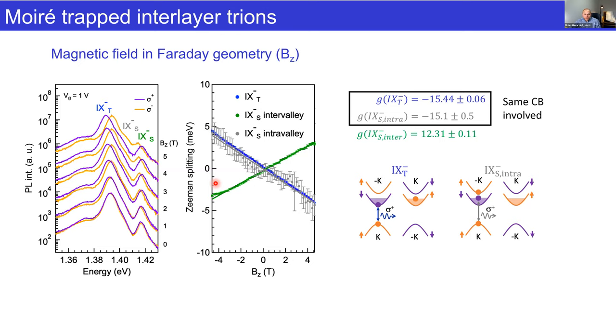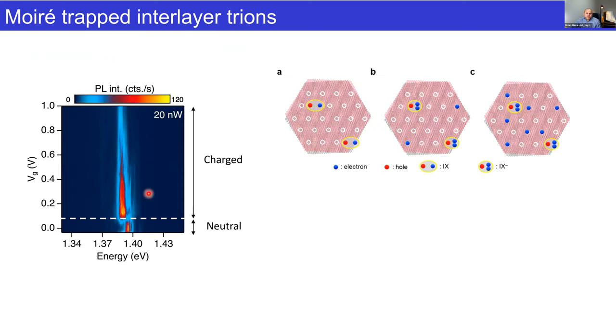So now this is the high excitation regime. If we go to the low excitation regime, this picture here, we can think about a Gedanken experiment, what would happen. We start in the neutral regime, where the white circles are the atomic registries of the moiré lattice, and we can imagine there's just a very dilute density of interlayer excitons shown by these red and blue circles. As we then change the Fermi energy, we start to get carriers doping into the moiré lattice, and they might go into these different positions.